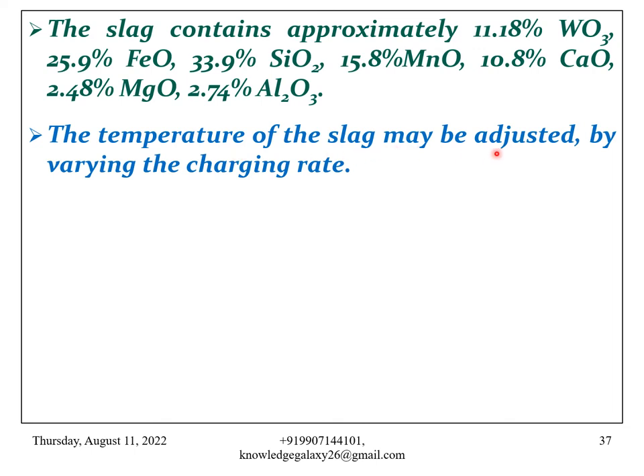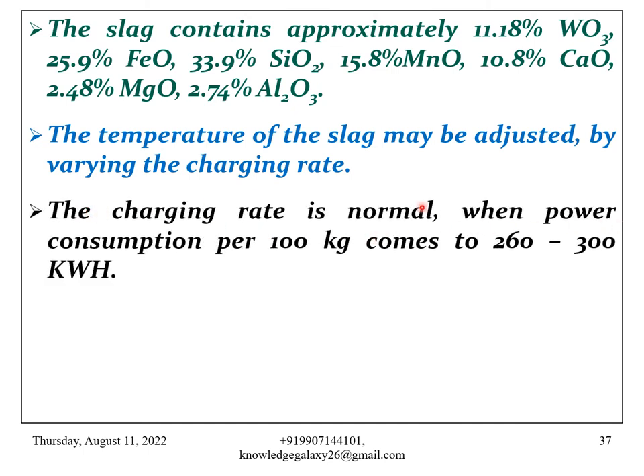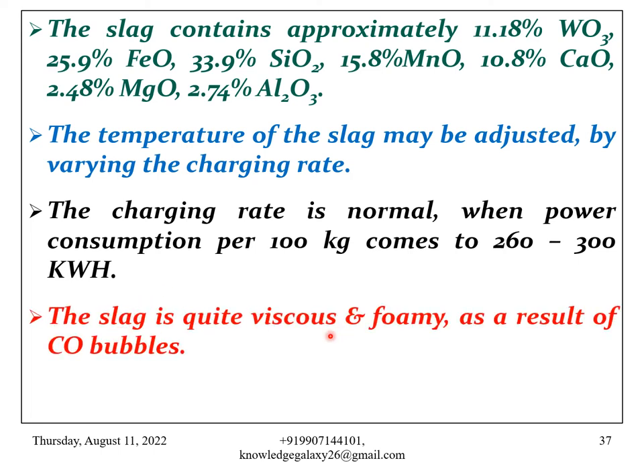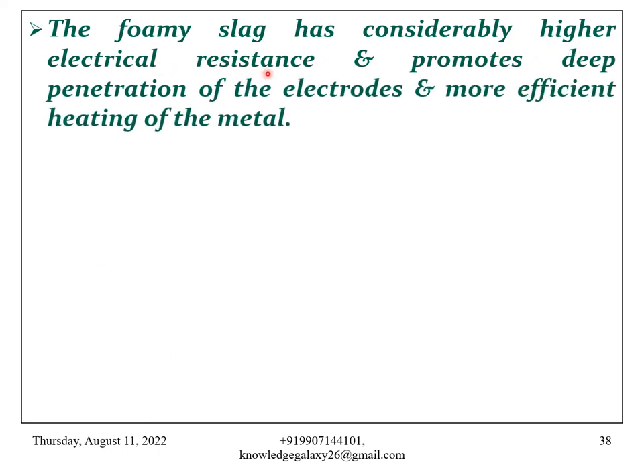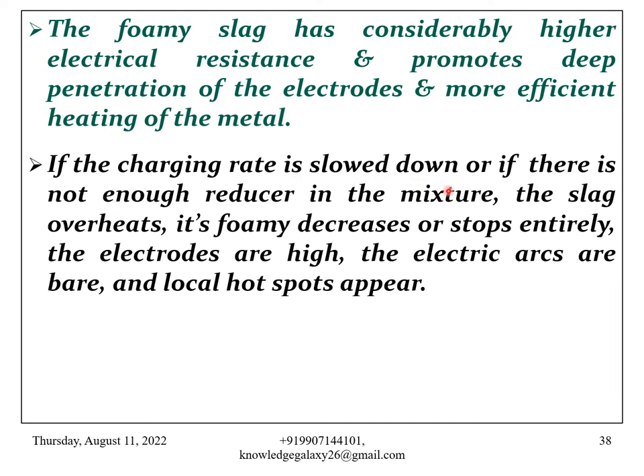The temperature of the slag may be adjusted by varying the charging rate. The charging rate is normal when power consumption per 100 kg comes to 260 to 300 kWh. The slag is quite viscous and foamy as a result of CO bubbles. The foamy slag has considerably higher electrical resistance and promotes deep penetration of the electrodes and more efficient heating of the metal. If the charging rate is slowed down or if there is not enough reducer in the mixture, the slag overheats, its foaminess decreases or stops entirely. The electrodes are high, the electric arcs are bare and local hot spots appear.